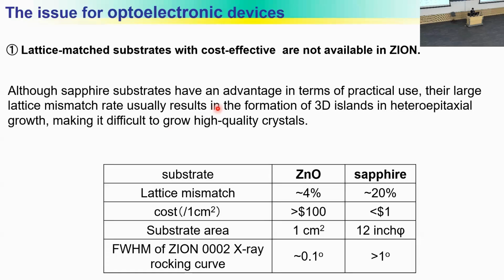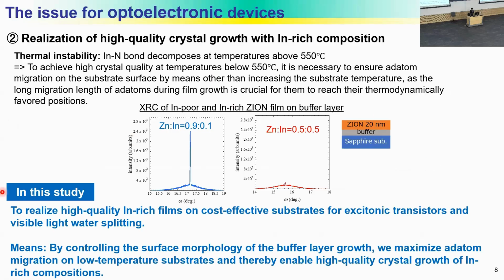However, lattice-matched, cost-effective substrates are not available for ZnInON. Sapphire substrates are very superior in terms of quality, productivity, and cost, but low crystal quality is caused by a lattice mismatch rate of over 20%. Another problem is a limitation of growth temperature due to the thermal instability of indium nitride bonds.